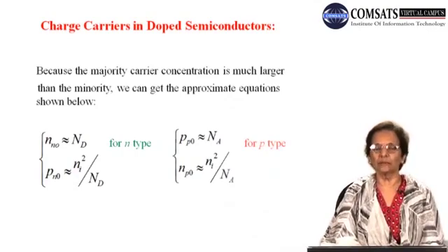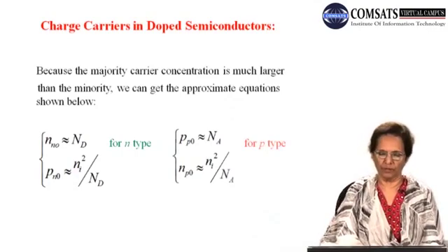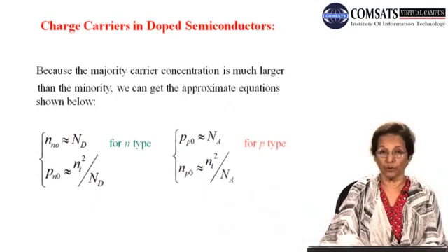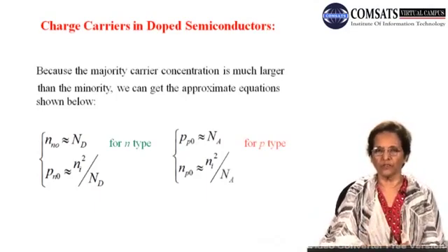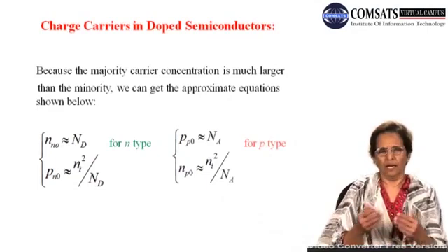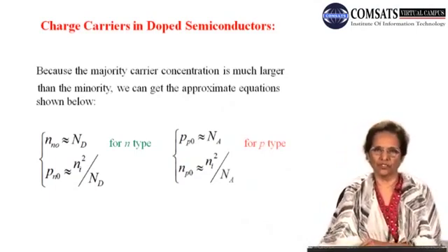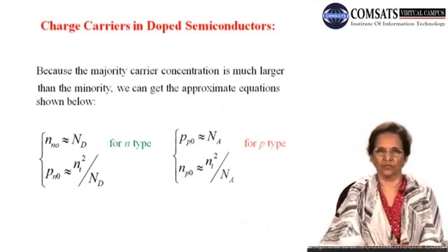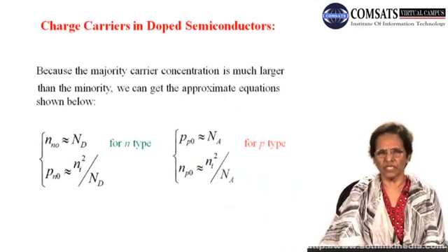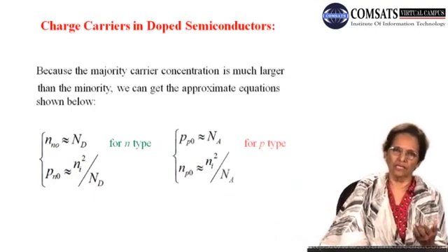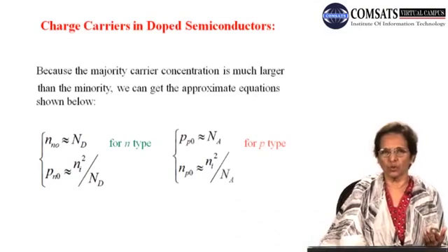So we use another important terminology for the doped semiconductor materials, which you see in this transparency. If the material is doped with a donor impurity that comes from the fifth group of the periodic table, then to a first approximation, we will discuss this carrier concentration and density of states in the next few slides, we can approximately say that the amount of donor added to the pure silicon crystal, the concentration of the donor impurity, is equal to the concentration of the free electrons in the n-type material in thermal equilibrium.